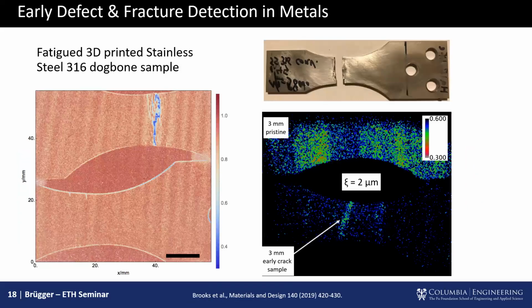Now, probably as a structural engineer, the most enticing capability is just doing neutron grading interferometry, NGI, on, for example, fracture samples. So what we can do here is, here we have xi, the autocorrelation length. That is essentially the spacing of the grading. So you can tune your grading to the specific repetition length of your defect to say, well, I know that nucleation, say in 316 stainless steel, generally occurs at the 2 micron level.